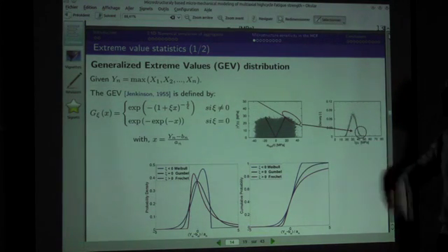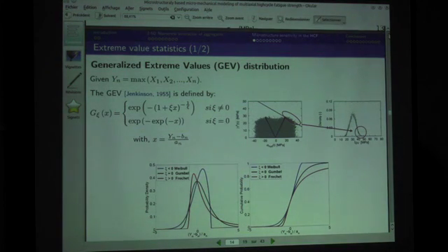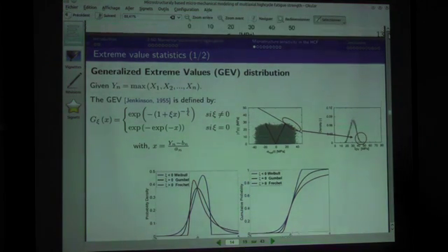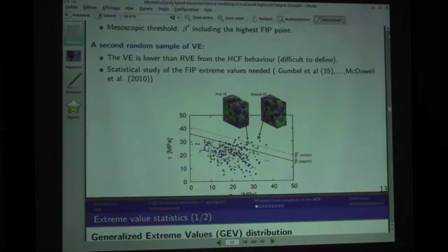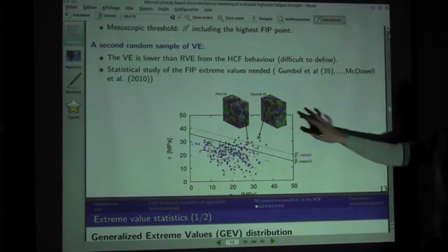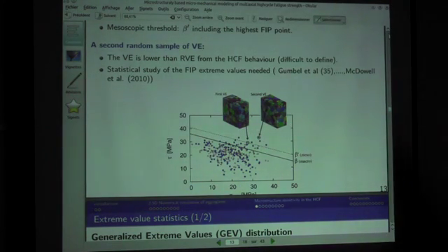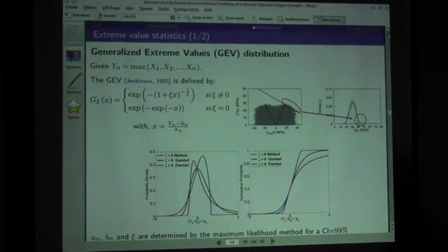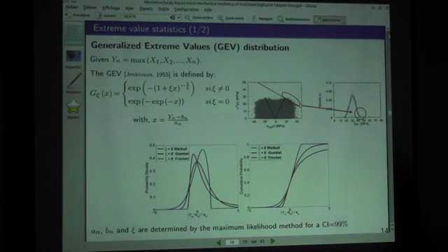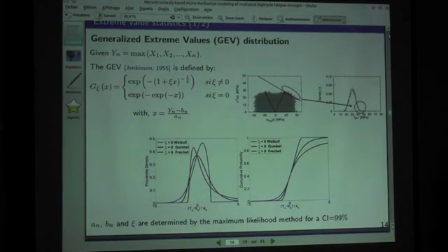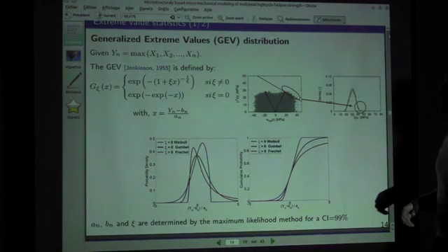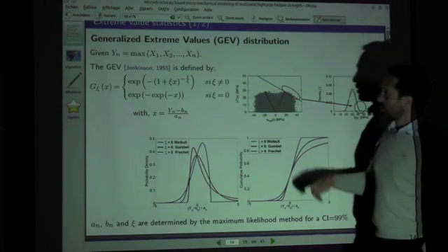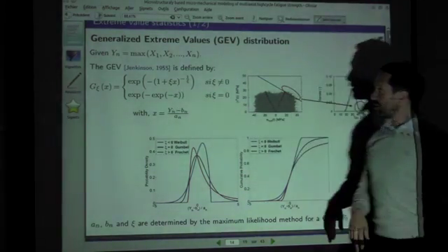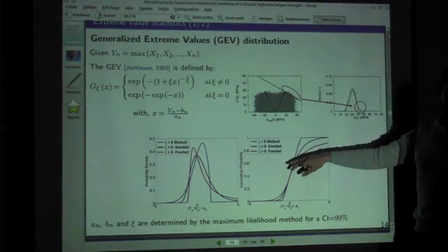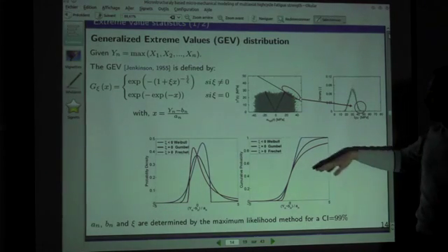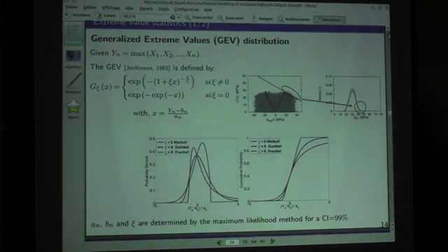So what we do is we're going to use some descriptions of the extreme responses, which are the set of responses obtained from the previous computation. So what we basically do is many computations, obtaining the extreme values and fitting some distributions for these extreme values. The most efficient one is the one proposed by Jenkinson in 1955, who proposed a general formulation for the extreme value distribution, which I will not go into detail, but depends mostly on this parameter, xi. Depending on the value of this parameter, you are shifting from one distribution to the other, going from Weibull to Fréchet, going through Gumbel for the parameter equal to 0.